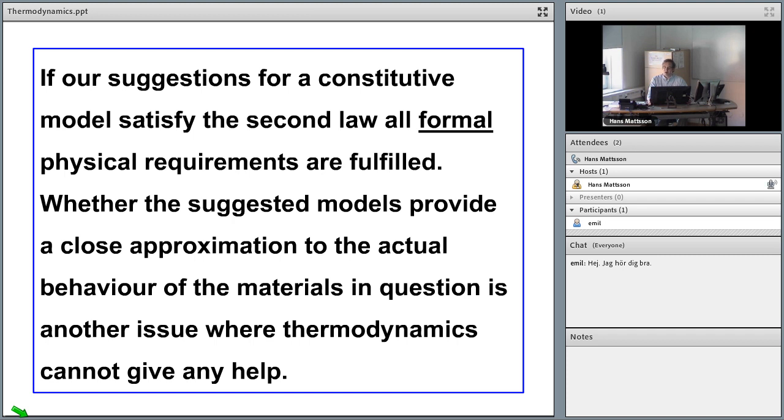I know that if you have a constitutive model that is not okay from a physical point of view, then it can be wrong if you run it in such a way that, for instance, you can win or lose energy and so on. You can do things that are not physically possible with the constitutive model. But you can anyway have a model that is good to simulate material behavior for a certain experiment that you calibrate the model to.